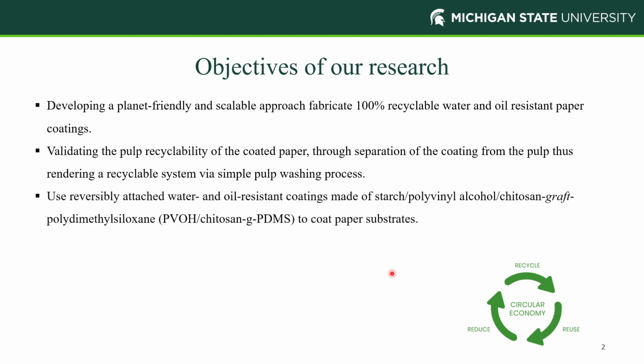And in order to produce this coating, we use reversibly attached water and oil resistant coatings, which are made from majorly starch and polyvinyl alcohol, and also a novel copolymer developed by our group which consists of chitosan grafted to polydimethyl siloxane in order to produce these coated substrates.